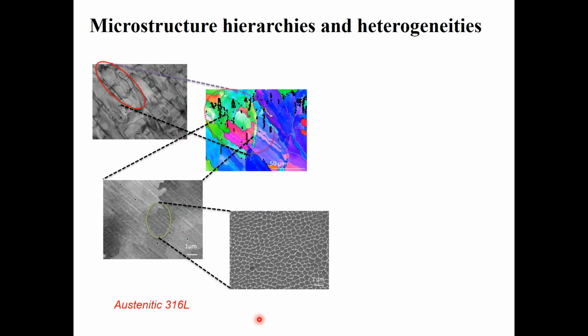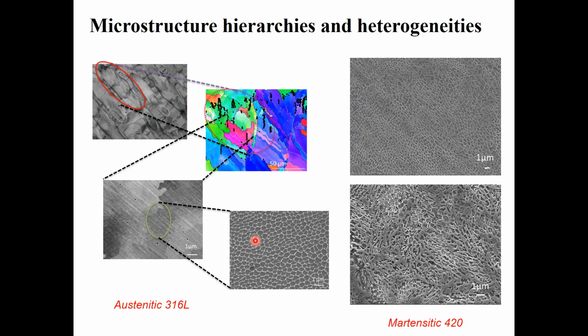So I will go a little bit deeper into this microstructure, and here you can see a scan. And if we go further within this scan, we see bigger grains. And if we go further in these large grains, we see subgrains of very small size, around 500 nanometer. So it is a hierarchical microstructure which has laser scans, and then grains, and then subgrains. And here is the microstructure of martensitic 420 SLM, and you can see a similar hierarchical microstructure is obtained. And you can also see the martensite needles there in the SLM built sample.